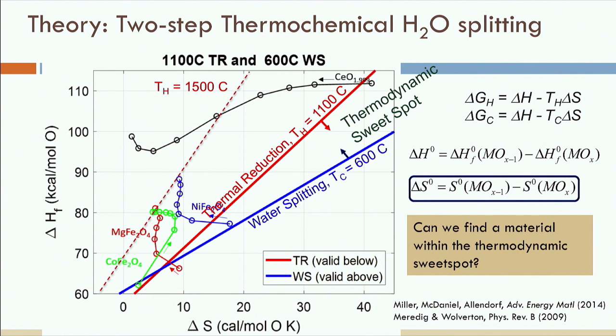Now this may seem easy, but it's not, because it's a thermodynamic problem. If the thermodynamics doesn't work, the kinetics don't matter. If you look at the two reactions in the two-step, the delta G for both of them has to be less than 0. If you are in the red line, which is the high temperature one, anything below that line is thermodynamically feasible. And for the low temperature reaction, anything above the blue line is thermodynamically possible. Now, if you are operating at 1500 degrees Celsius, the region between the 1500 dashed line and the blue line is relatively large. You try to get to 1100 degrees Celsius, and that window shrinks. And so you've got a thermodynamic sweet spot which is really small.